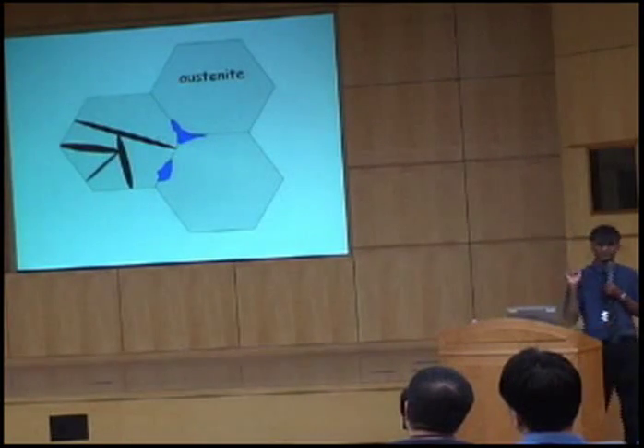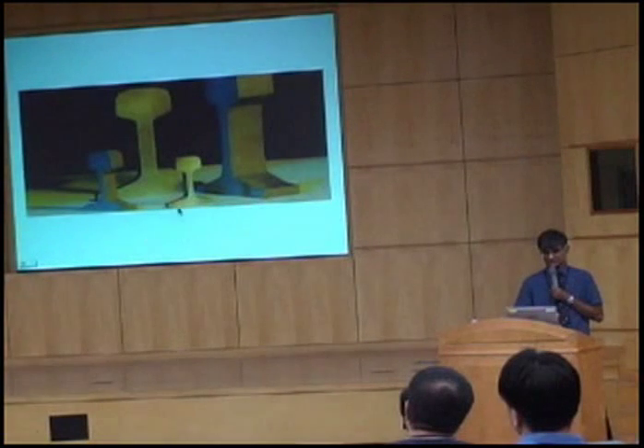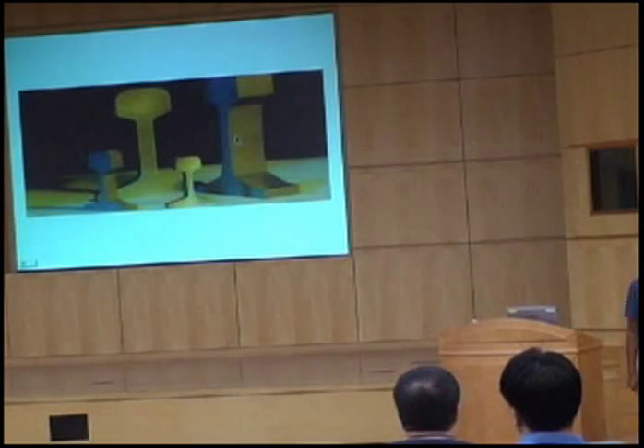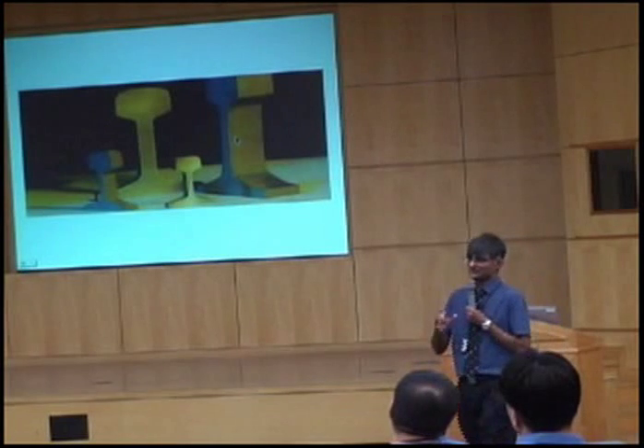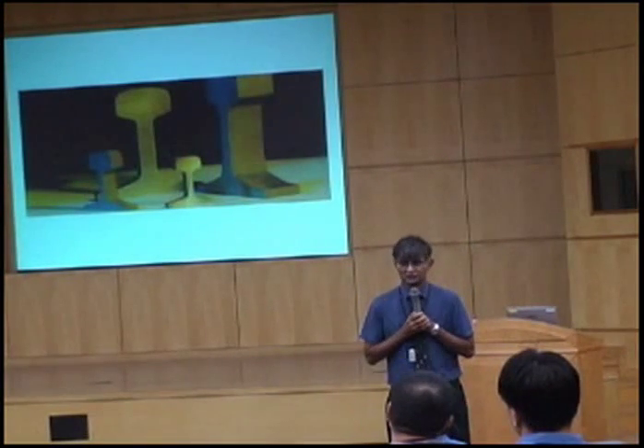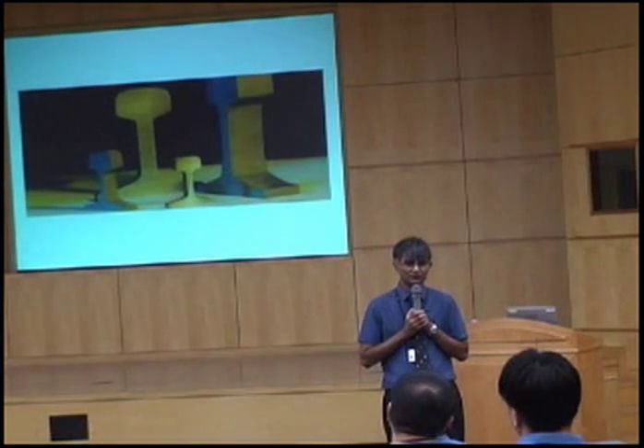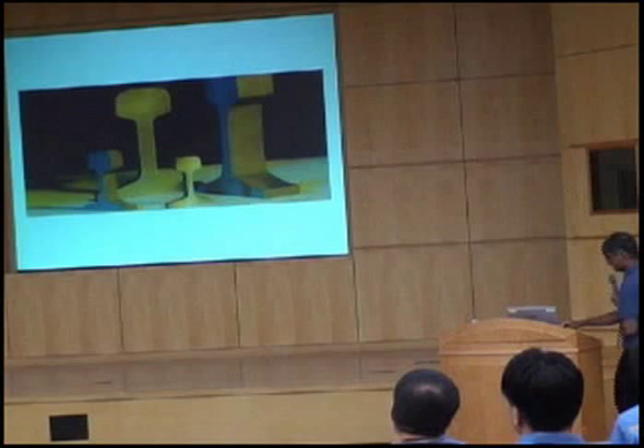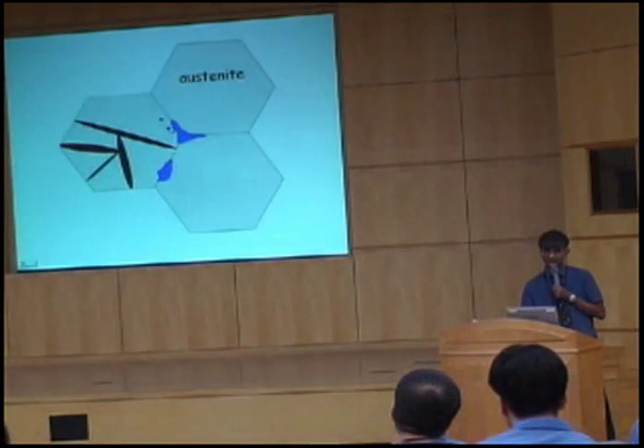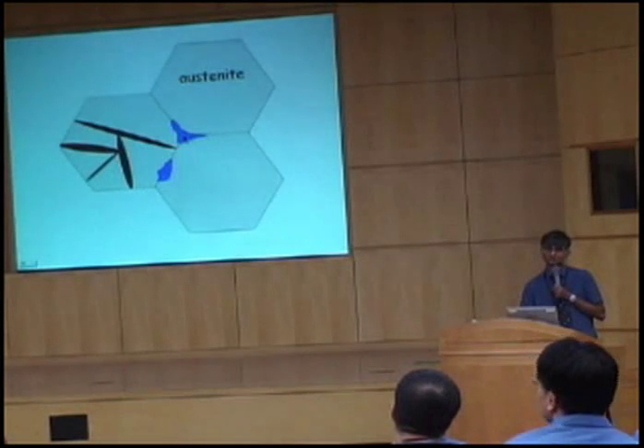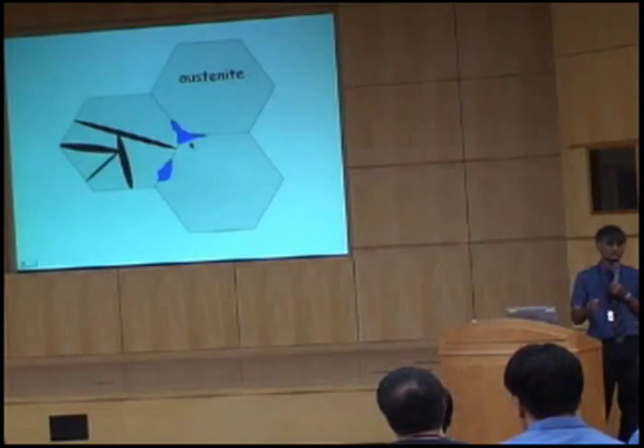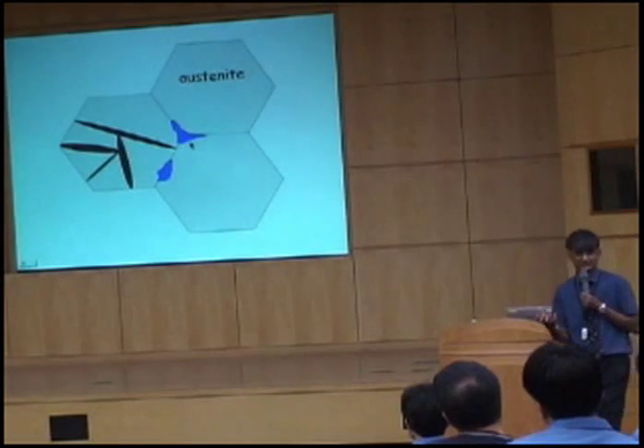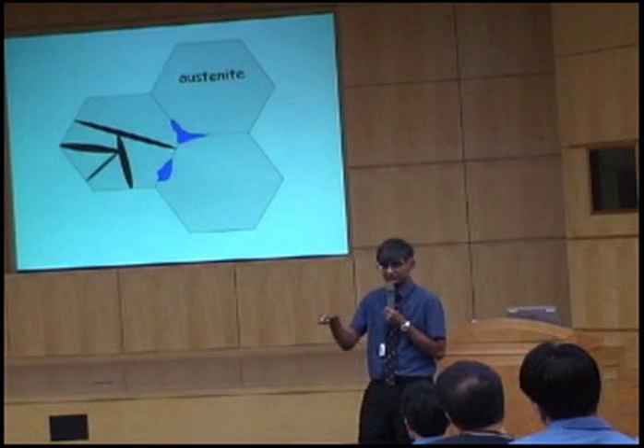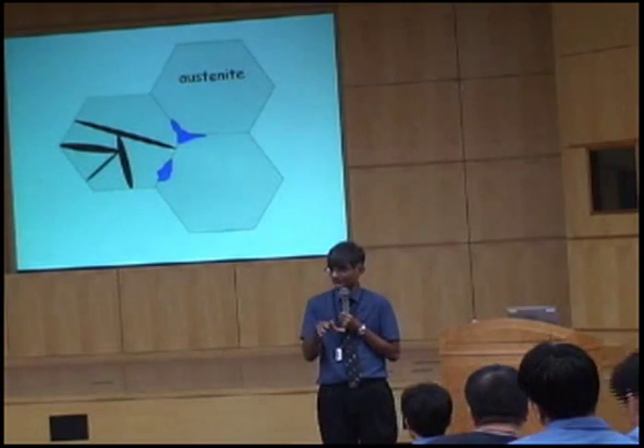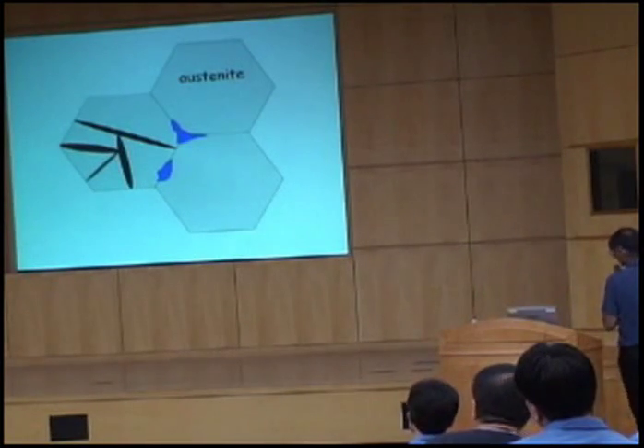And one problem is that when we made these steels, the small rails were fine, but the large rails turned out to have very poor fracture toughness. Now remember, I said to you yesterday that with displacive transformations, plates cannot cross austenite grain boundaries. So they are limited to the same austenite grain, in contrast to diffusional transformations where ferrite can grow across grain boundaries and destroy the prior austenite grains. With displacive transformations, you are left with prior austenite grain boundaries where impurities segregate. And of course, that's also true of bainite.